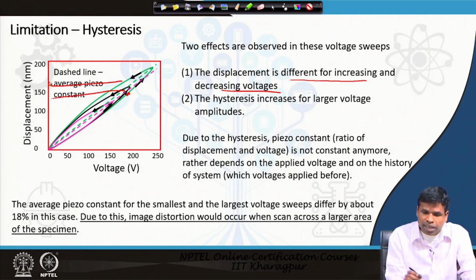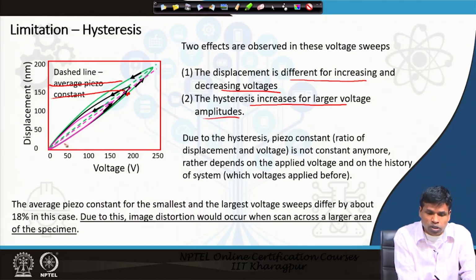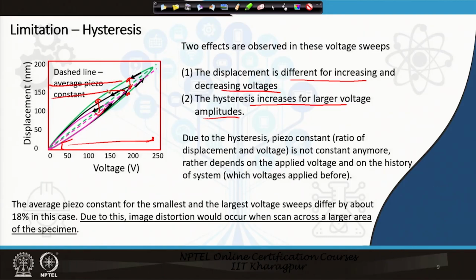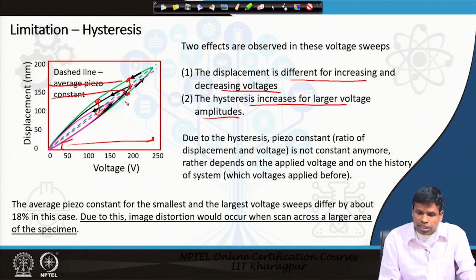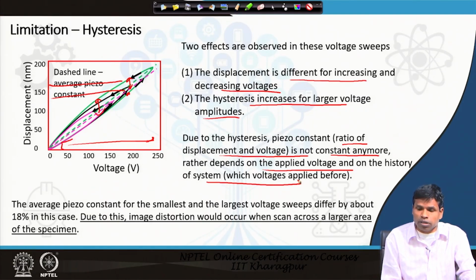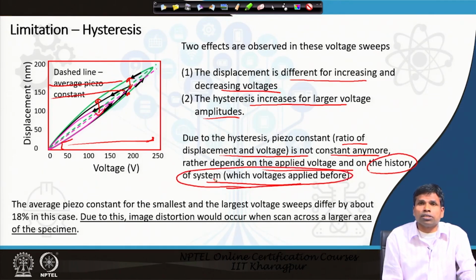This is one thing we see, and second thing is the hysteresis increases for larger voltage amplitude. As we go to a larger voltage range, then this hysteresis amplitude is increasing, this green curve. And due to the hysteresis, the piezo constant, the ratio of the displacement and voltage, is not constant anymore. It depends on the applied voltage and on the history of the system, which voltage was applied before. So, this is the important factor that gives the hysteresis to the system.